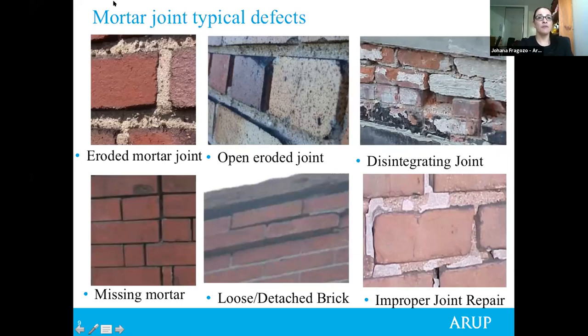Then we have missing mortar, which is similar to the other types of defects on mortar joints, mainly due to inadequate construction practices, or the disaggregating of the lime due to water presence. And here we have improper joint repair. This is quite common. We see this quite commonly when doing inspections, and it usually is because of the lack of compatibility between the existing grout material and the repair material being used, and the lack of sufficient depth on the repointing.